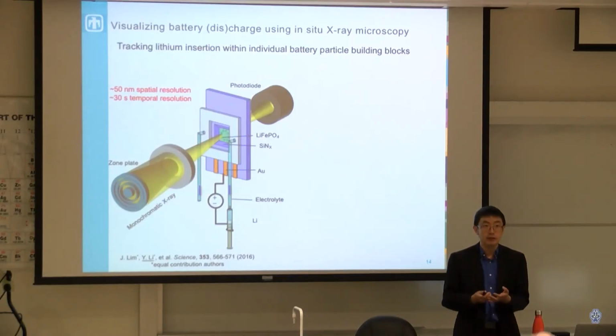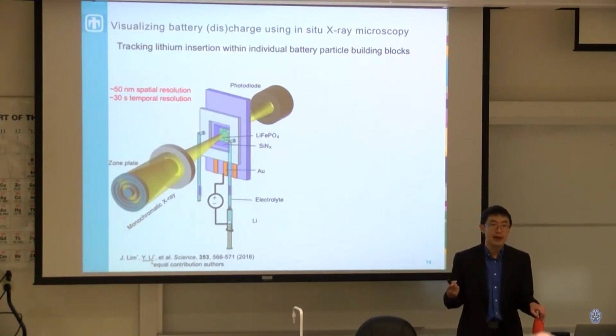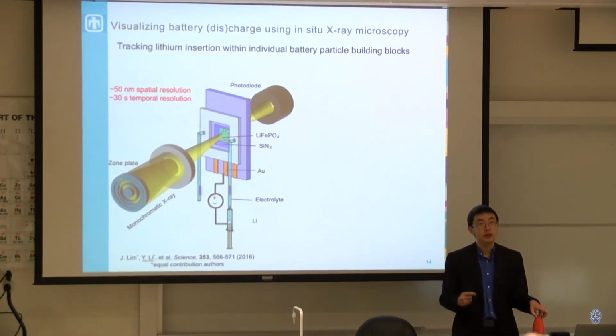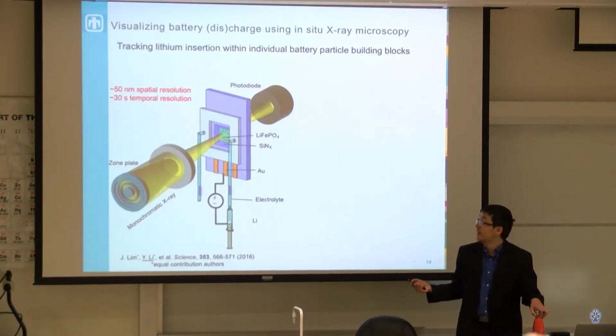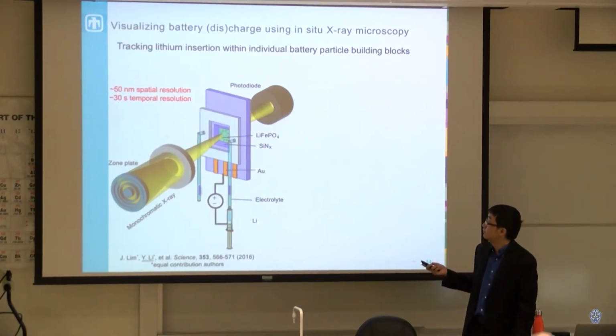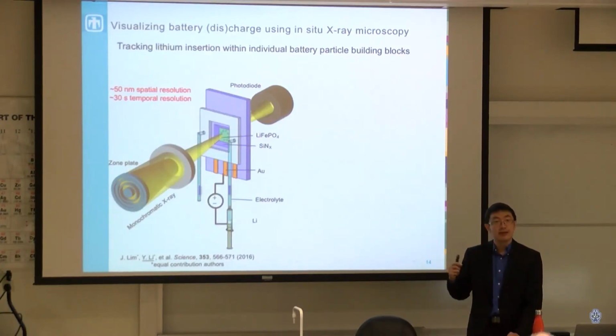So what we found in this material is that if you have a lithium on the side versus an iron, if you have lithium, you reduce iron from 3 plus to 2 plus. And the iron 3 plus has a different spectroscopic signature than the iron 2 plus. So we use that to determine where the lithium is. And furthermore, we can scan it, so we can get a microscopic picture of what's happening here as well.